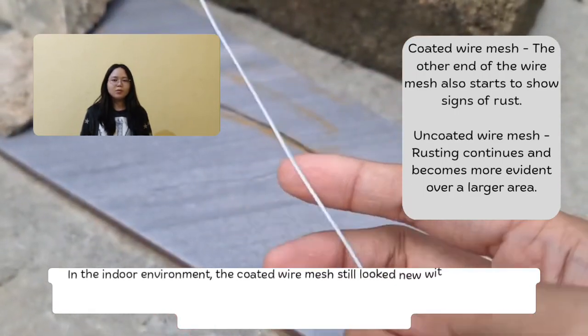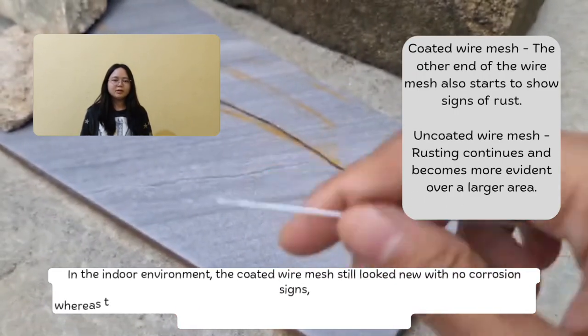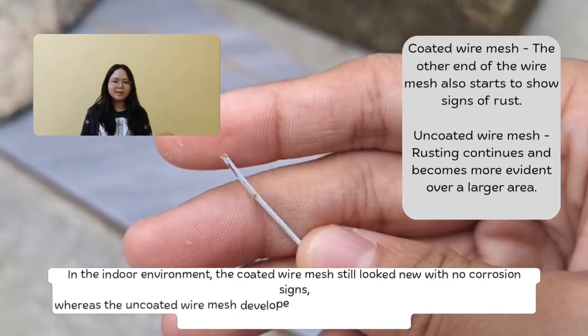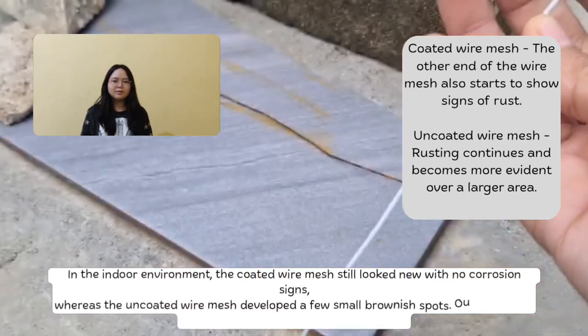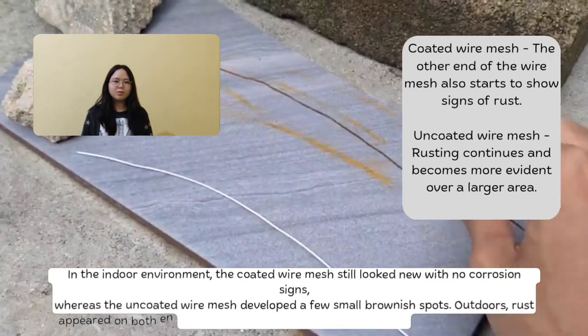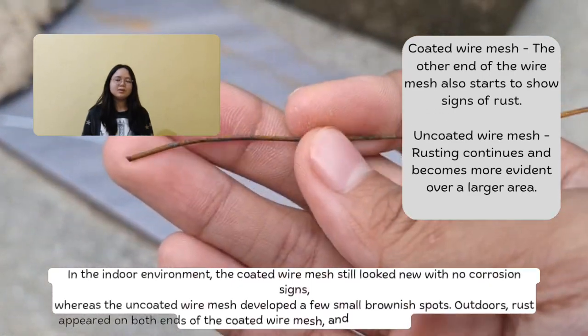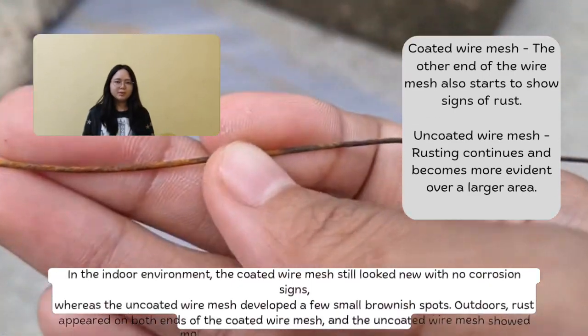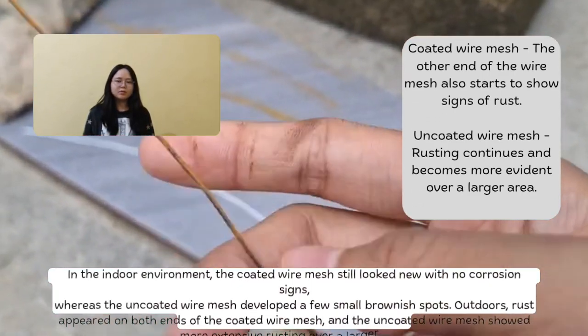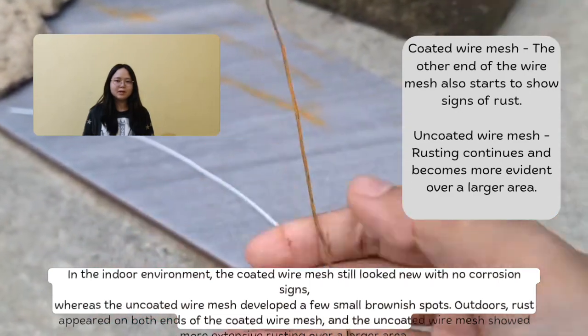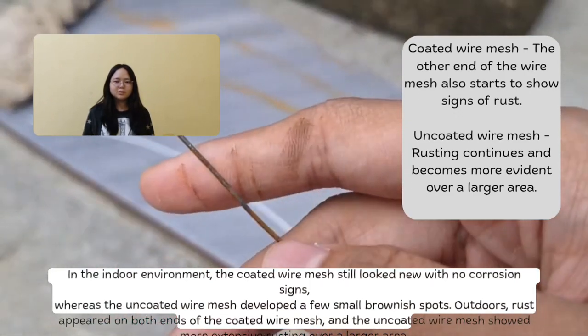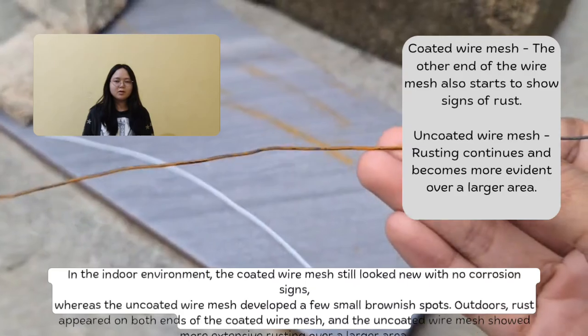The coated wire mesh still looks new with no corrosion signs, whereas the uncoated wire mesh developed a few small brownish spots. Outdoors, rust appears on both ends of the coated wire mesh, and the uncoated wire mesh shows more extensive rusting over a large area.